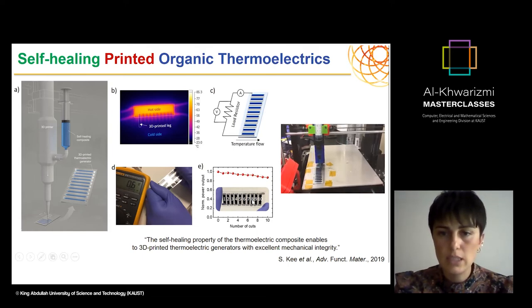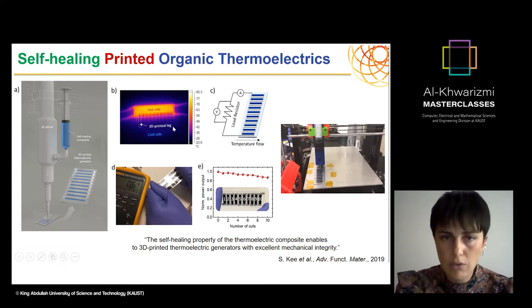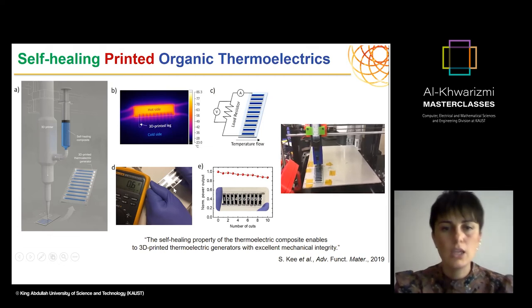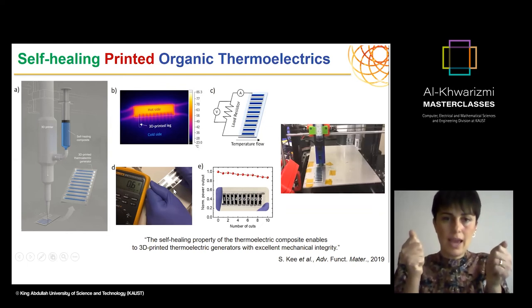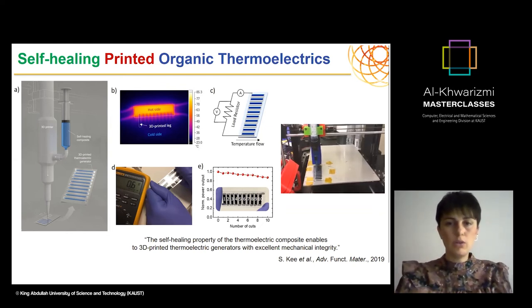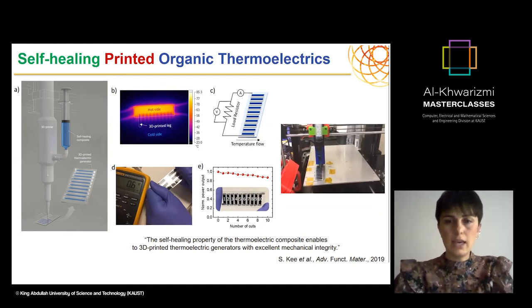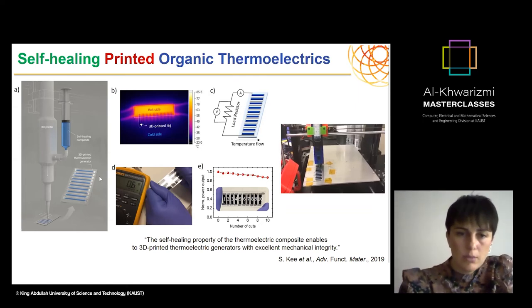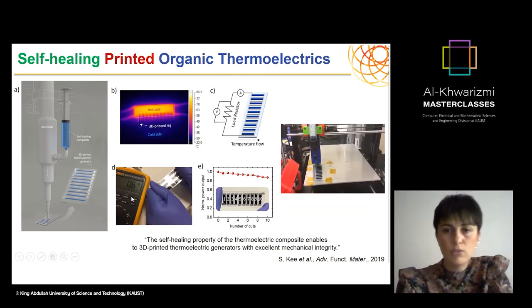And as you see here, we were successfully able to print the PEDOT ink with this 3D printer. And you see here the legs for the thermoelectric with the PEDOT, and we combined it with a silver paste as an N-type leg. And when you look at the IR camera, you could actually see the hot side, which was on a hot plate, and the other side of the module was actually cold enough. And when we could hold it with our hands at room temperature, where we only create, I think, a 7 Kelvin difference, we were able to generate actually 0.6 millivolts in this case.